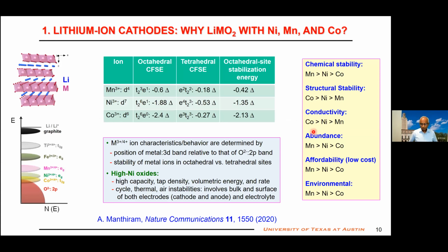So right now, the cathodes we use, they're all composition LiMO2, where M is a mixture of nickel, manganese, and cobalt. The question is, why do we have to use 3 metal ions? Can't we do it with 1? 2 major factors. The first factor is the relative positions of these redox energies with respect to the top of the oxygen 2p band. In the case of cobalt, cobalt 3+/4+ overlaps with the top of the oxygen 2p band. Therefore, if we charge more than 50%, we will pull out electron density from the oxide band.